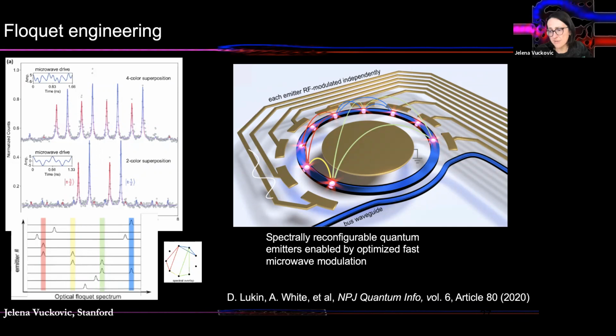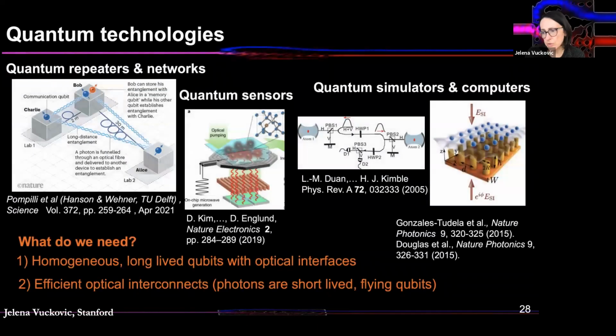And even more recently, we started looking into more complex tuning of these color centers to overcome inhomogeneities. So it's not just a simple Stark shifting with the DC signal to tune the transition, but also optimizing the driving on the transition to control the output spectrum. So it's related to the idea of Floquet engineering, so that you can completely control the spectrum of your color center at the output by applying a particular driving microwave signal. And this was done in silicon carbide, but of course it's applicable to diamond as well. So now, that's one piece of the puzzle, right?